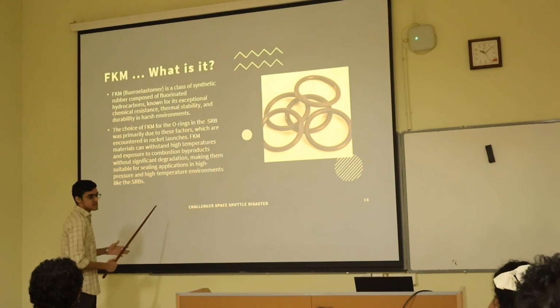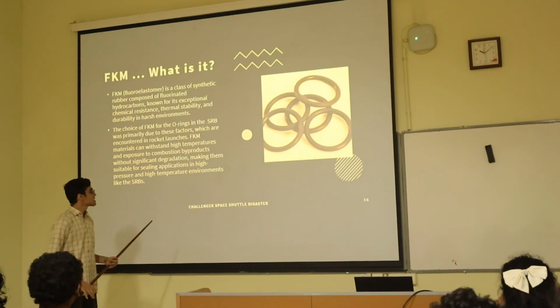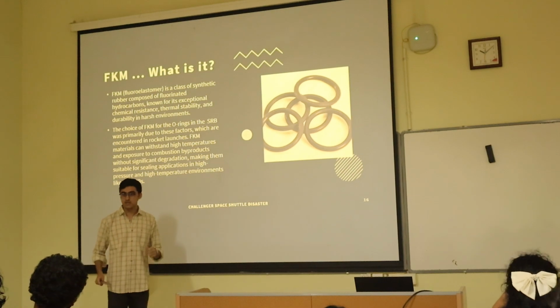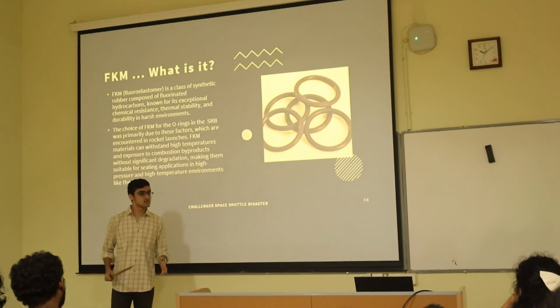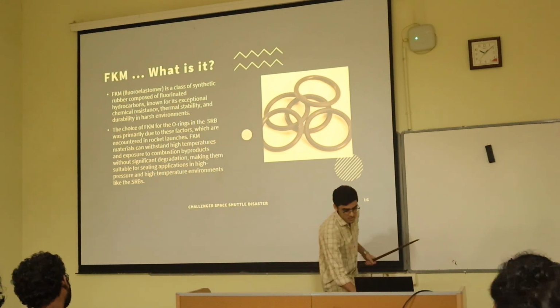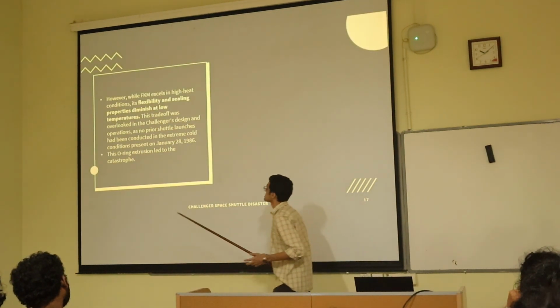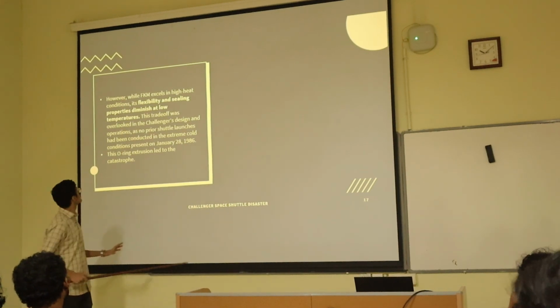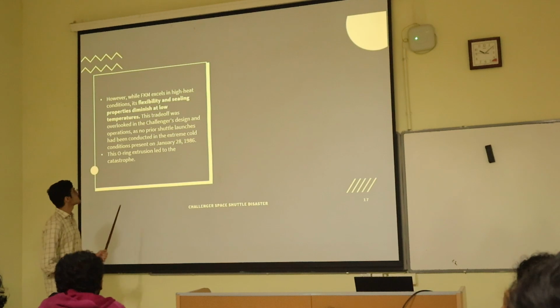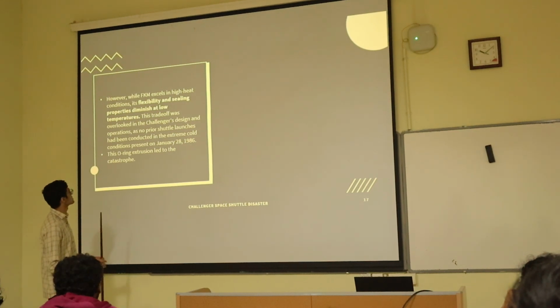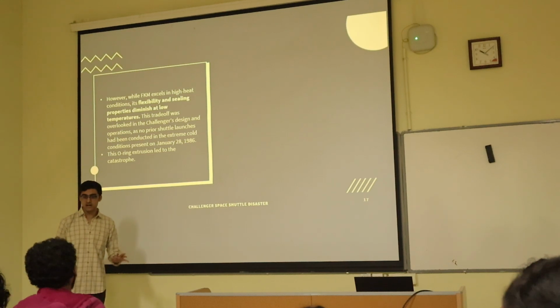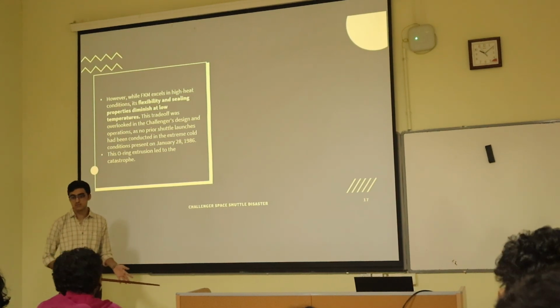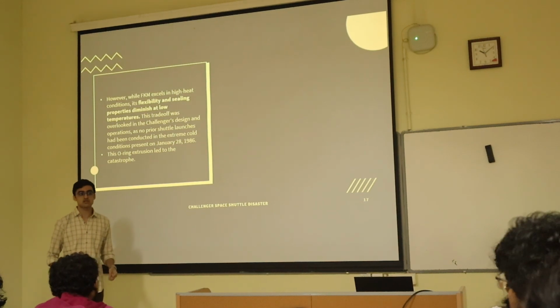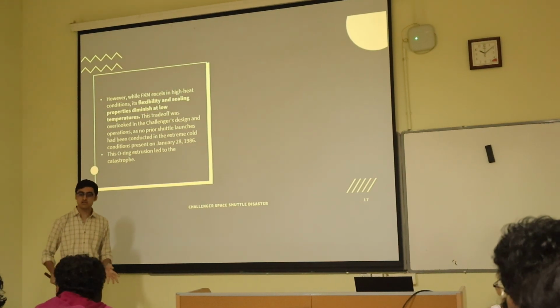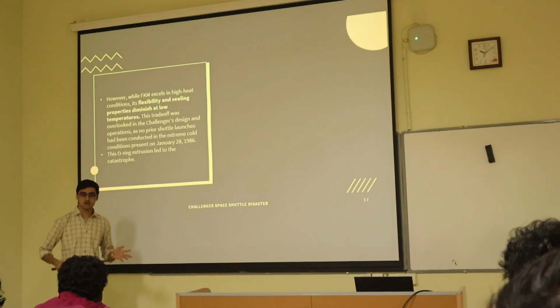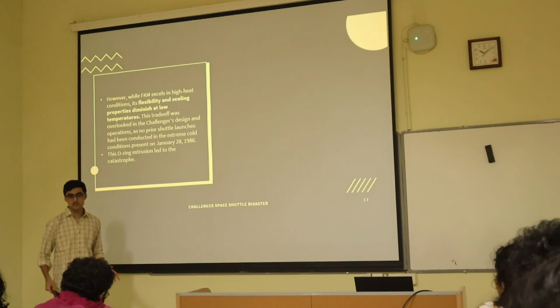So FKM can withstand very high temperatures and very high pressures. But what happened on that day was that there were very low temperatures, and that was the reason for the failure. As written here, FKM excels in high heat conditions, but the main issue arises when the flexibility and sealing properties deteriorate at low temperature. This was due to the partial transition to the glassy regime. As the temperature drops, the relaxation time increases, and because of the relaxation time increase, the local stresses are increased. So because of that, fracture can occur.